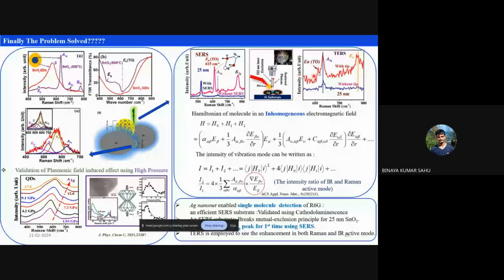And here what happens, generally the mutual exclusion principle was broken. Those who know about the mutual exclusion principle, the Raman spectra and IR spectra could not be seen simultaneously, unless and until there is some perturbation or there is a loss of the center of symmetry. And here what we could see, this is the IR peak at 615, and that peak was coming out when we were doing the TERS, tip enhanced Raman spectroscopy. And that is because the mutual exclusion principle breaks in the presence of the local plasmonic structure.